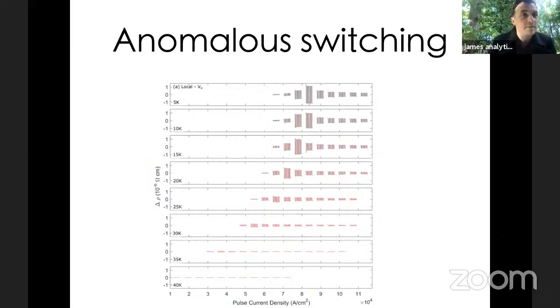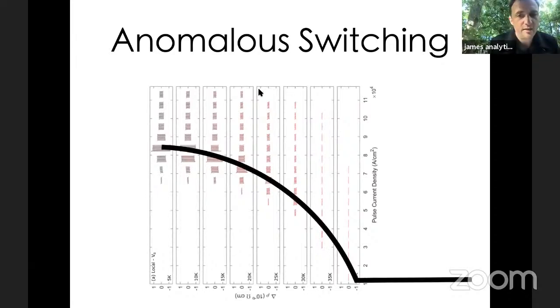First, let me demonstrate that this really is associated with the magnetic order. What I've shown you here is the current dependence at different specific temperatures as you go across the Néel transition. At the Néel transition, you start to see the pulse train turn on. And what's interesting is that as you go to colder and colder temperatures, the current you need to apply to turn on the switching becomes higher and higher, which basically tells you that the current at which you see the switching, the threshold current, is a proxy for the order parameter. It measures the antiferromagnetic gap. All I need to do is rotate this, and you can see very clearly that it looks like an order parameter growing. So the switching threshold really turns on like an antiferromagnet.